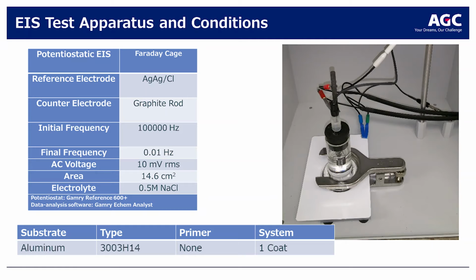Here's the apparatus. They use a silver electrode and a graphite rod as the counter electrode. They start at an initial frequency, and then they change the frequency over time, and they'll get graphs that look at the changes over the frequency, over the life of the coating.